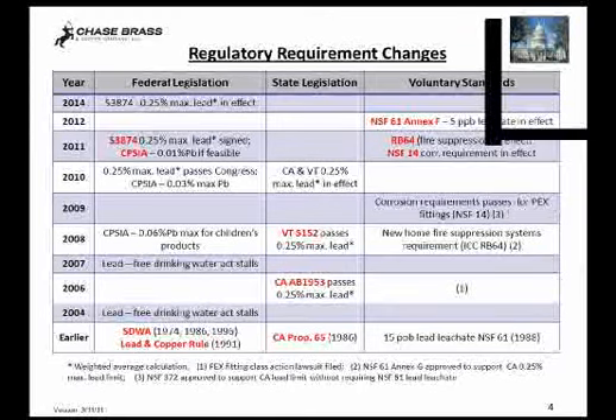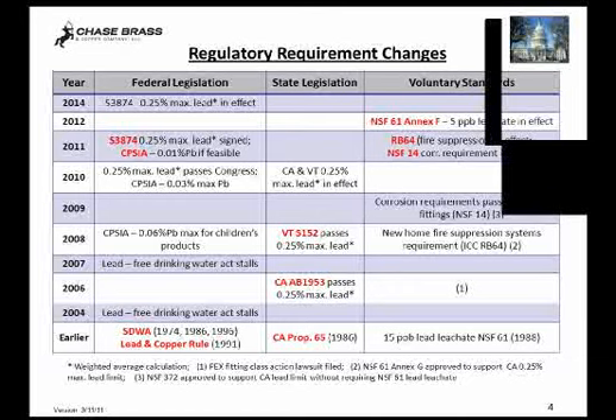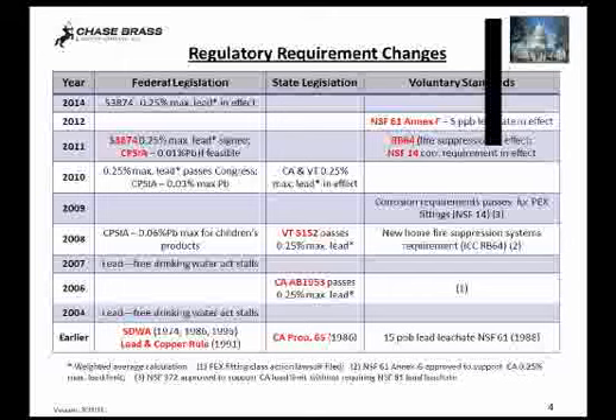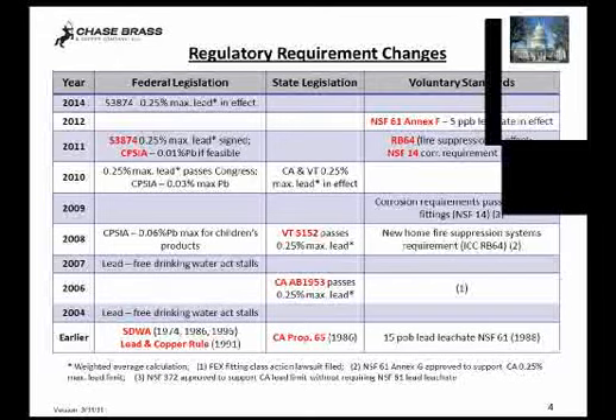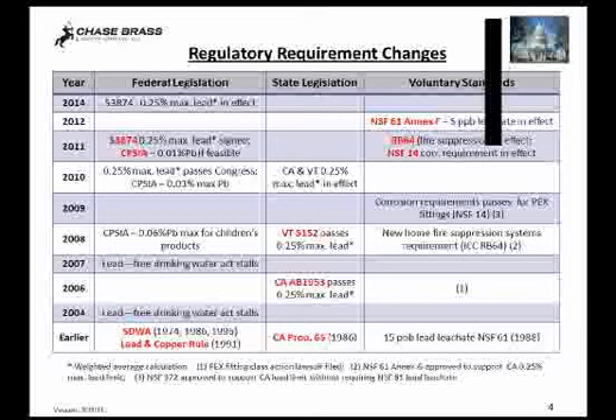The International Code Council passed a fire suppression standard, which says that all new 1- and 2-family homes beginning in 2011, where this has been introduced into the municipal codes, have to have a fire suppression system, in other words, sprinklers in every room. And those are tied into your drinking water systems in the home and are designed to ensure that the materials that are used work as required by incorporating NSF 14, which is for PEX standards. And PEX standards are the plastic tubing that now are used in many homes to convey water around as opposed to soldered copper tubing. And NSF 14 has some corrosion requirements that had not been seen before, but were a reaction to some corrosion failures in Nevada and Minnesota earlier in the decade.